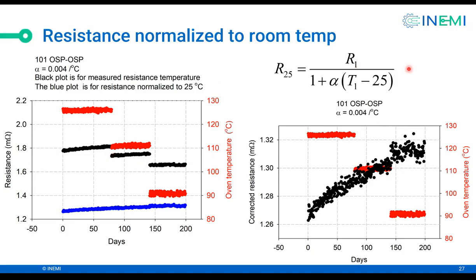So we use this equation here on the top right. We say, okay, at temperature T1, resistance is R1. But what will the resistance be if, in our mind's eye, we cooled the sample to 25 degrees C? So this would be the resistance at 25 degrees C. And alpha is not known, but we use an alpha that gives us a good fit. Notice, by the way, this blue line and this black line are the same thing, but in this right plot we expanded the scale. So notice there are no jogs in this because we chose a good value of alpha, which is 0.004. We got rid of the jogs.